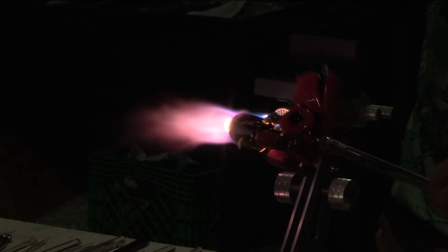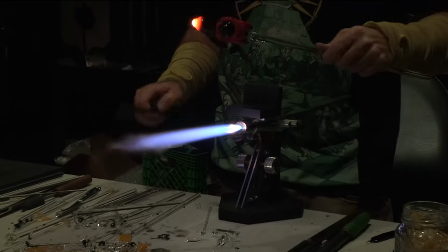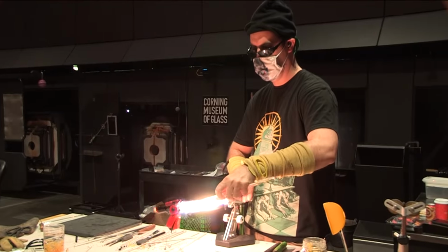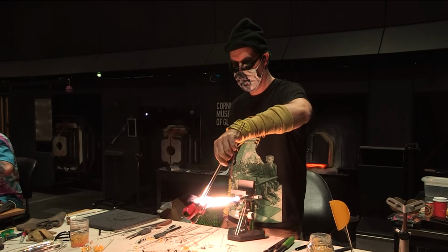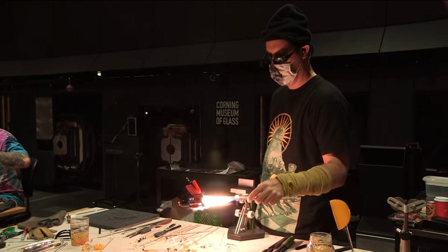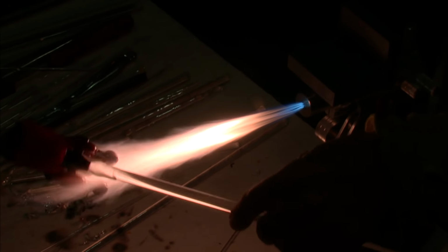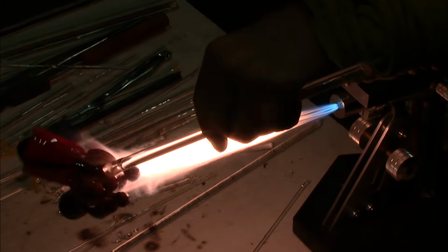if a lens is a softer glass or a glass that expands and contracts more with temperature change, as you go to use it in different temperature conditions, the optics change. That lens is gonna either expand a little, contract a little, and that little bit of movement can really affect your optics of a telescope or a microscope. So some German scientists led by Otto Schott developed a glass by adding boron oxide to it that would not expand and contract nearly as much as most other glasses. So it made for much more effective, much more consistent lenses.